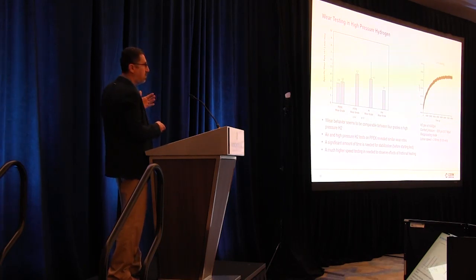As they absorb more and more hydrogen, their growth continued, and we got a stabilization at around 20 hours. So that's when we could actually start our wear testing. So we had to have a stabilization process before the testing.